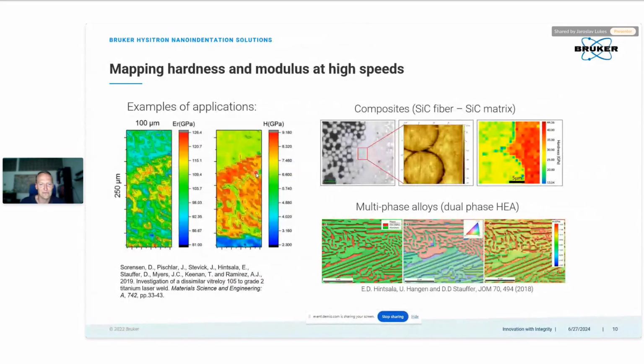So if you do all this, think about indent spacing and your indentation depths, and you have nice and sharp probes, then you can do very interesting and nice studies on different materials over even larger scales. You can really go from a micro scale to hundreds of microns scale. As you can also see in this example, the hardness map on this alloy is giving quite a nice contrast, because the hardness is very much related to the different phases that you have, and it's measured very locally. The elastic deformation zone is actually very, very big, so you might measure the average properties right from the beginning. So hardness is giving a very nice contrast.